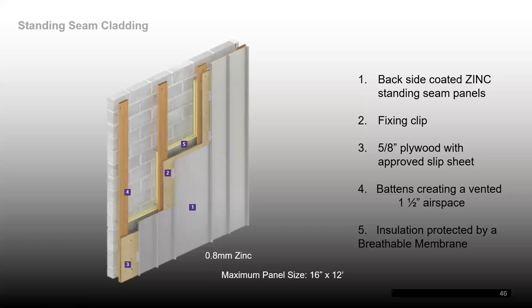For standing seam panels, they will never be completely flat, but if you use a 0.8 millimeter thick zinc and single lock panel 16 inch wide will help reduce this. For installation ease, it is recommended that panels be no more than 12 feet in length.